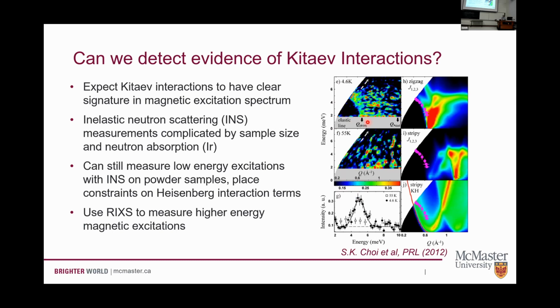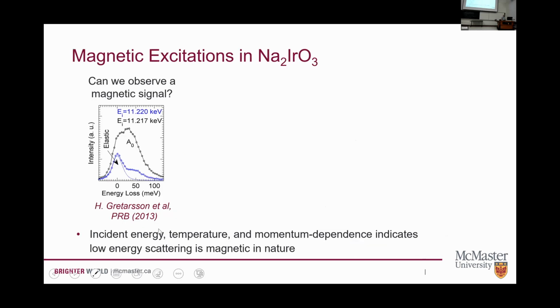So you're supposed to believe this is a magnetic peak here that looks like this. You can use this data to maybe constrain the terms that might be in the Hamiltonian. But what we're going to try and do is use RIXS to look at higher energy excitations to maybe probe different energy scales. Okay, so what we fight with RIXS is that it's very difficult to get to very low energy things. And so we're going to try and use this neutron and X-ray complementarity.